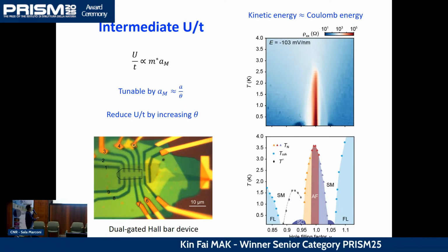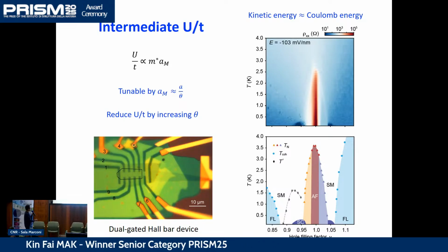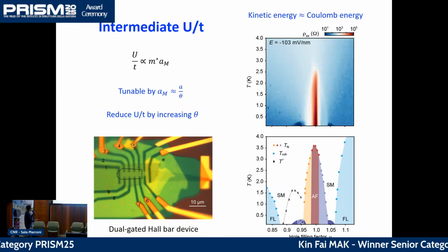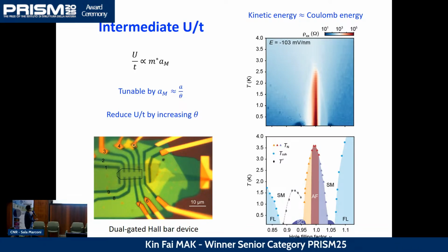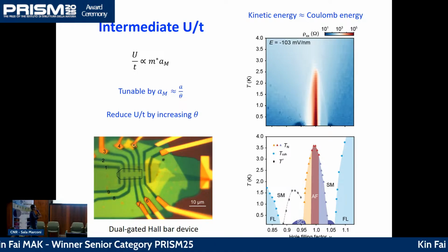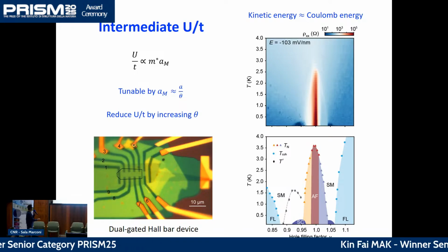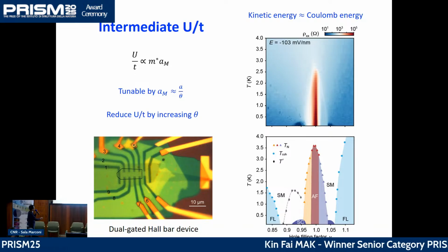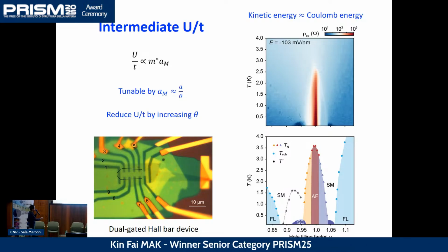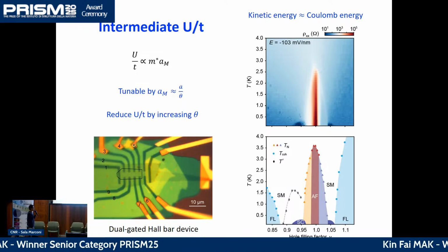By just tuning the kinetic energy to be roughly the same as the Coulomb repulsion energy, what I'm plotting here is the resistivity map as a function of temperature and the doping density in the system. And this is filling factor 1, that corresponds to 1 electron per Moiré unit cell, or half band filling. This is in log scale, so when you see the very blue region here, that means nearly zero resistivity. When you see the red here, that means very high resistivity, like an insulator, okay?